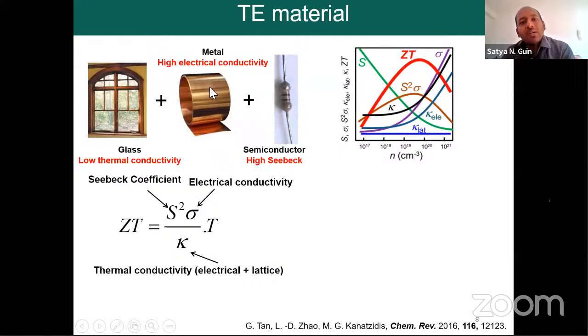That is possible to achieve in a metallic-like system. We know that metals generally have very high electrical conductivity, and at the same time we need a very high Seebeck coefficient. That is possible to achieve in a semiconductor-like system. In the literature, people have seen that all these three properties generally get optimized in a 10 to the power 19 to 10 to the power 20 carrier concentration regime, where you can generally achieve a maximized ZT value of a system.